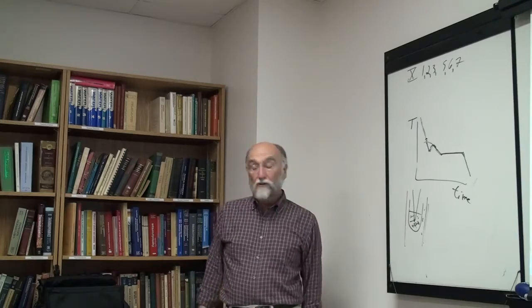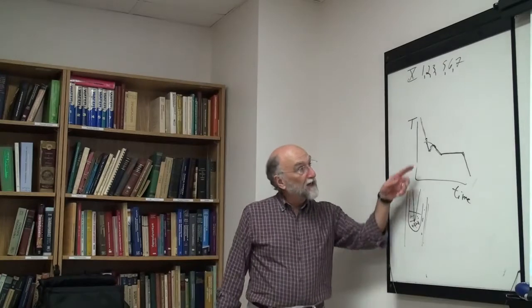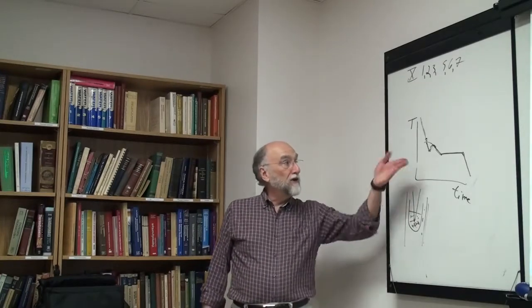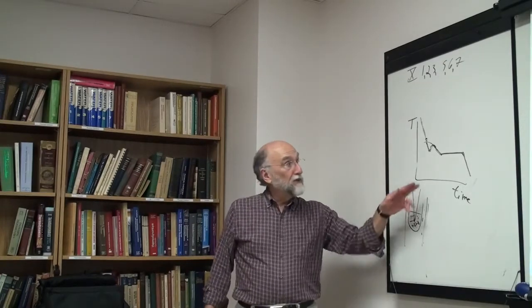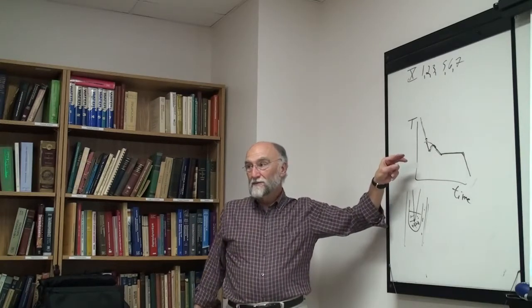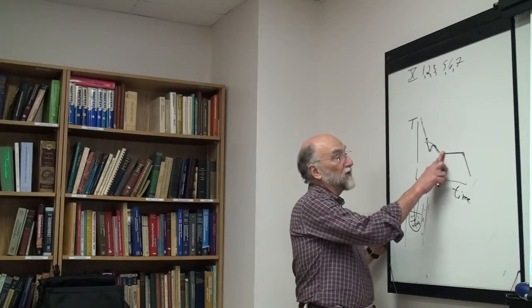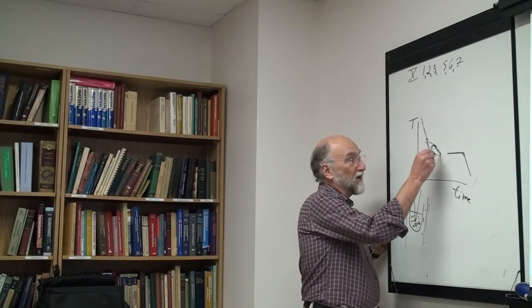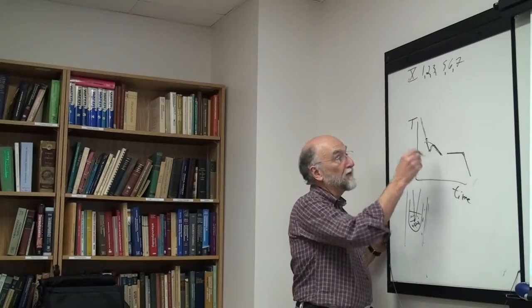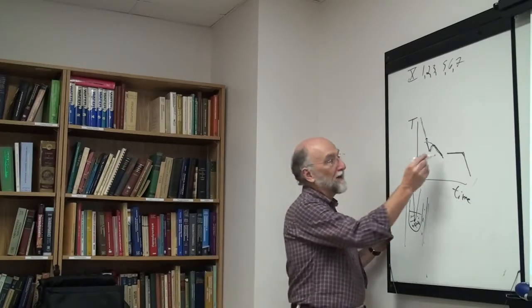But with a metal, without stirring or shocking it, it's quite easy to get supercooling of 20 degrees, and the temperature never comes back up again. So supercooling can be a big problem. And you also get supercooling when you hit the eutectic, because although the alpha phase is forming, the beta phase has to start to nucleate as well, and that doesn't happen either.